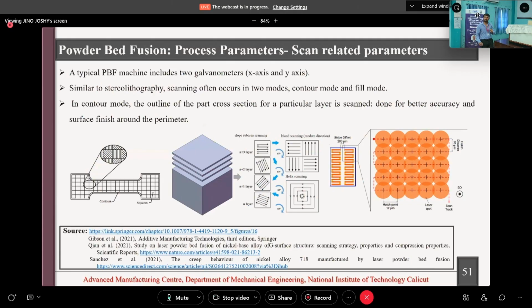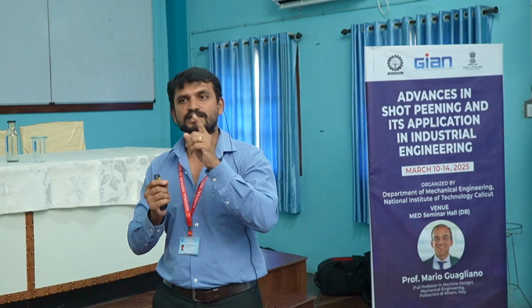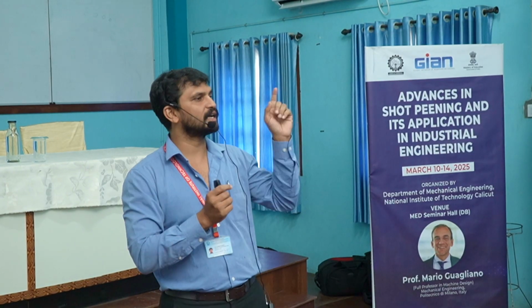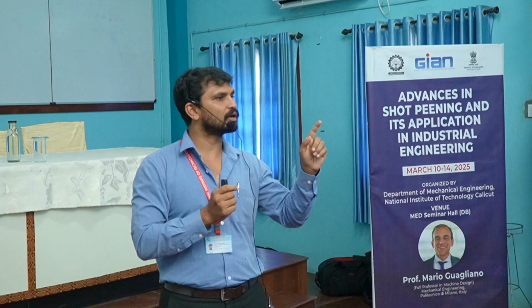So whenever we are dealing with additive manufacturing, especially laser powder bed fusion, we do end up with defects like porosities, small structures, and also unmelted powders in between. It's not mandatory. Our intention is to have less porosity as well as less unmelted powder, because this unmelted powder particle can act as a stress concentration point and the fatigue crack can initiate from that particular point.